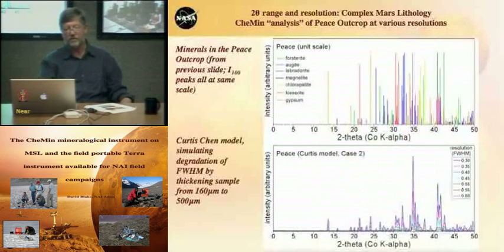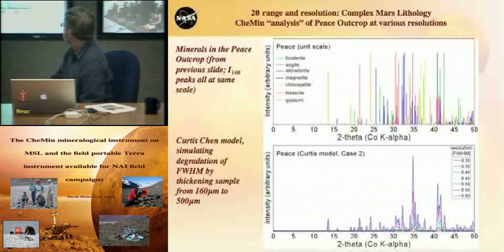What kind of resolution do we want? And we can't just have the best resolution possible because resolution is inversely proportional to count rate. So we want to have basically the worst resolution that will give us the answer that we can live with. So what we did is we made a model of these minerals and used various resolutions here from 0.3. I know you can't see the colors here all together, but 0.3 to about 0.6 degrees 2 theta.